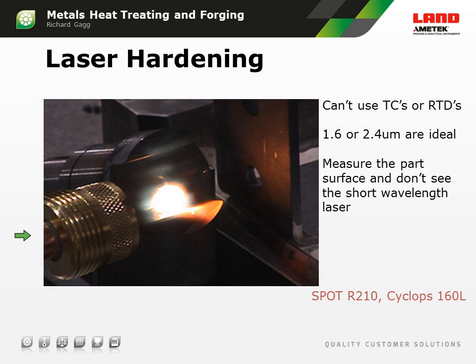This process is becoming increasingly used, because not only is it accurate and fast, but it's much lower cost than other methods of heat treating and hardening surfaces. Now, the lasers that are used for these kind of processes are YAG lasers, and YAG lasers typically work below 1.1 micrometers, so shorter wavelengths than 1.1. There are maybe four major wavelengths that YAG lasers use, and they come down to close to the visible, and then up to about 1.1 micrometers.